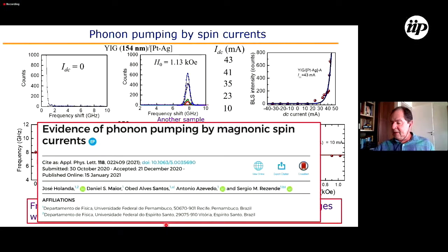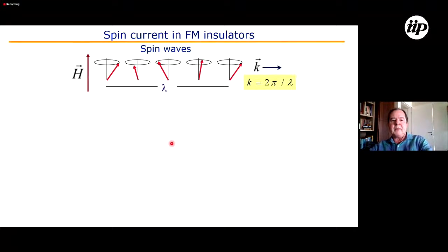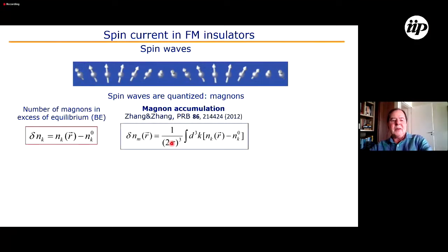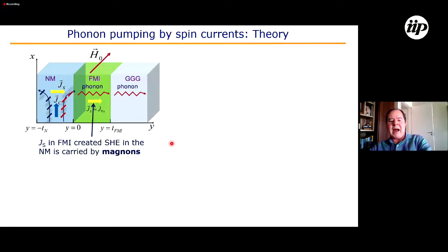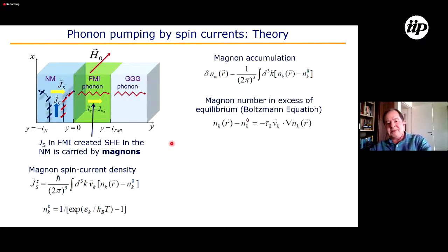And then we published this paper early last year, evidence of phonon pumping by magnonic spin current. In other words, a spin current in YIG, which is produced by magnons, creates phonons by phonon pumping, which is the reciprocal effect of the spin pump. Well, I don't have the time to show you the theory. There is a theory. The theory involves magnons, involves several things.